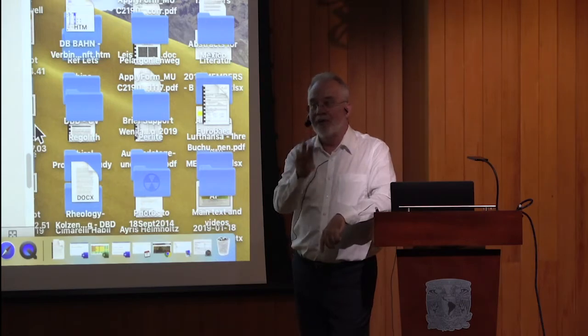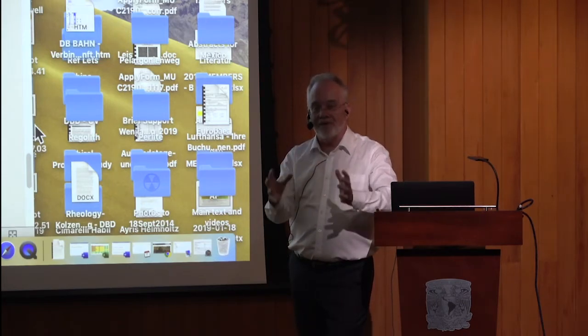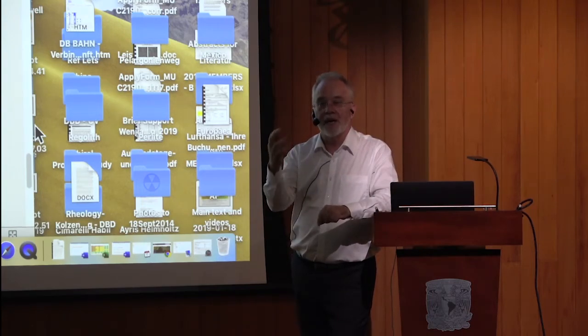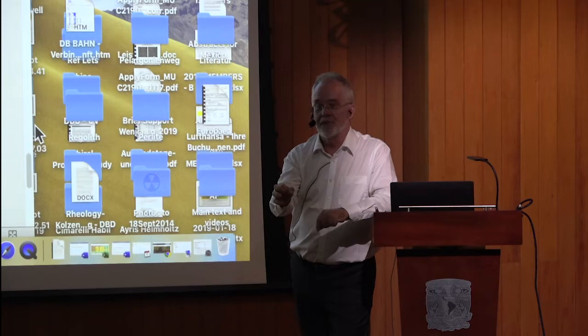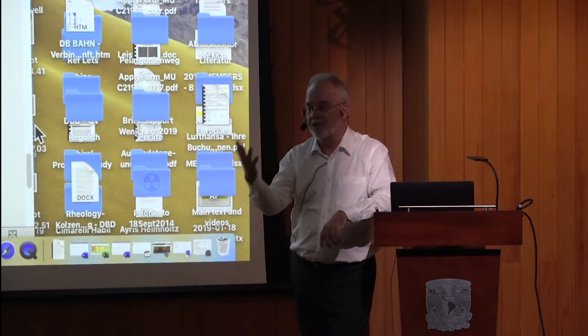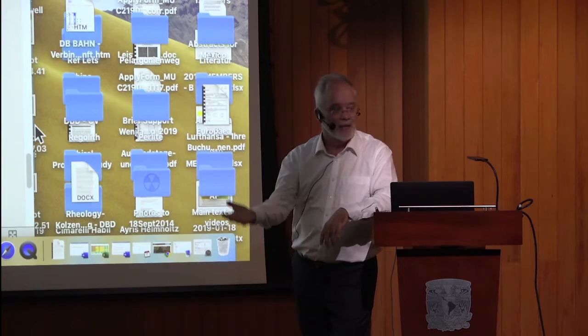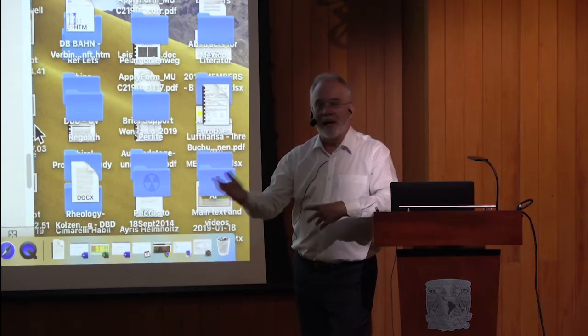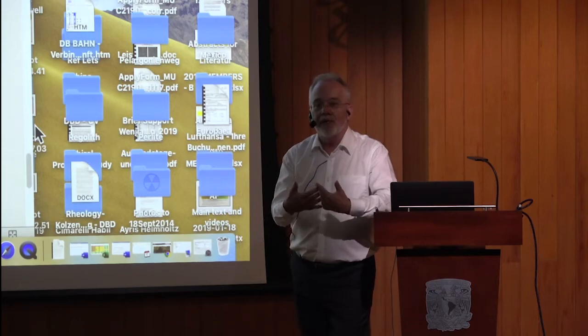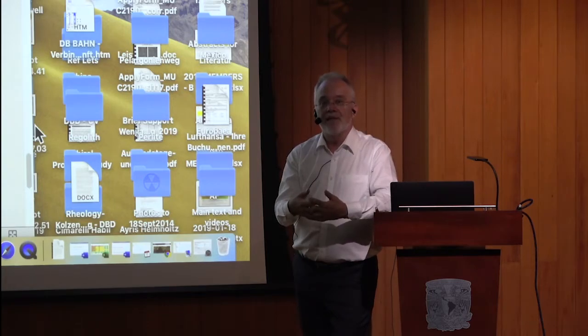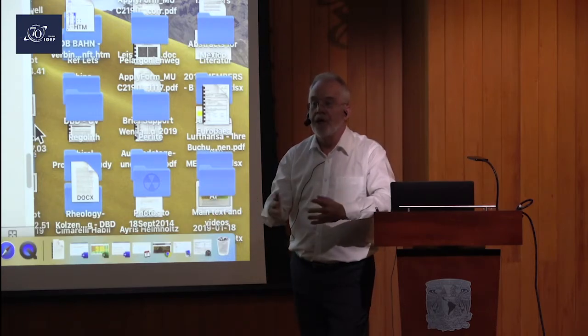And so the only way we can guarantee that we're doing anything roughly approximate is to make sure that our samples are much larger than the bubbles or the crystals. You know, this classic argument in rock physics that the sample must be 10 times as big as the crystallinity, otherwise you're going to get erratic results. So this is the way that we respond to this question of scaling. It is true that we are not worried about the fluid dynamic scaling, which is a literature, as you know, on these experiments. We're worried about the scaling of the length scale, which is characteristic for failure of these materials.